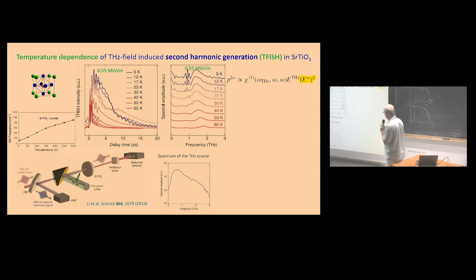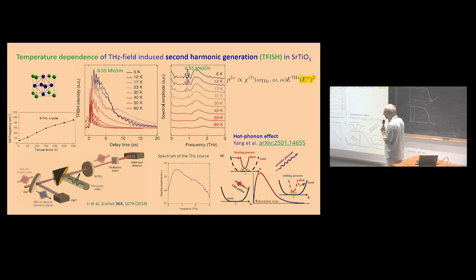But it's still a controversial result, because there is also another paper claiming that it is not a change of symmetry in this case, and that the second harmonic generation is not due to breaking of centrosymmetry, but is the so-called hot phonon effect. That is, you practically populate the soft phonons, and due to this, you change the interatomic potential and you generate the second harmonic signal. So it is still a matter of debate.